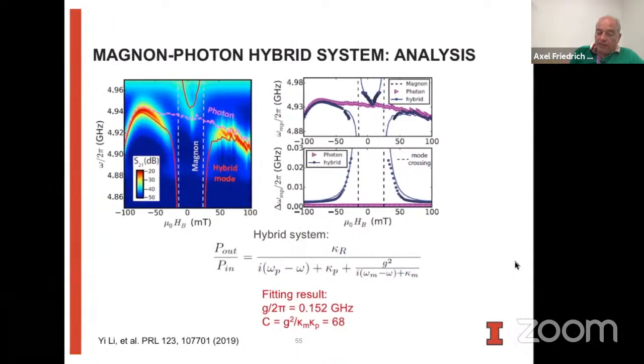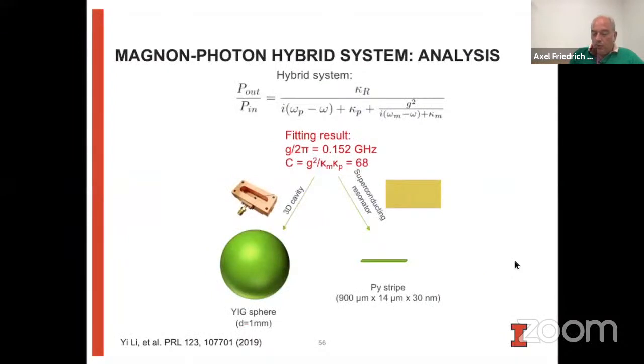So let's compare this a little bit further. If we compare this to the measurements that were previously done on bulk yttrium iron garnet spheres, as I said, for our result, we get a cooperativity of about 68, which is very comparable to what you get with these YIG spheres. But we have a magnetic system that is much, much smaller in volume than the yttrium iron garnet system.